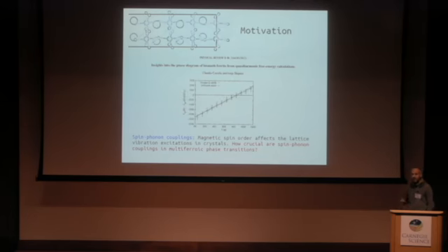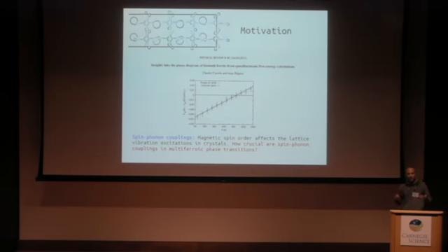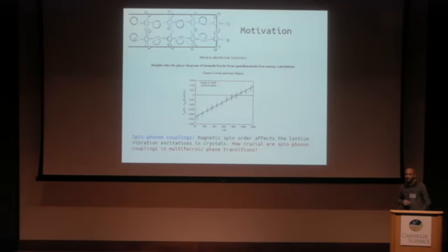We developed an extension of the quasi-harmonic approximation based on first-principles calculations in order to take into account the effects of magnetic disorder on the phonon frequencies. When you heat up a magnetic material, the magnetic moments start to fluctuate, and that has an effect on the vibrational properties. We wanted to take into consideration that temperature-induced magnetic disorder on the vibrational frequencies of the material.